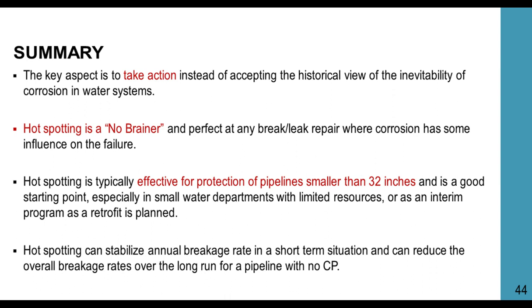Hot spotting is a no-brainer and is perfect for any kind of breaks and repairs when corrosion has influenced the failure. Hot spotting is typically effective for protection of pipelines smaller than 32 inches and is a good starting point, especially in a small water department with limited resources, and as an interim to the retrofit program that is being planned. Hot spotting can stabilize the annual breakage rate in the short term and can reduce the overall breakage rate over the long run for pipelines with no CP.